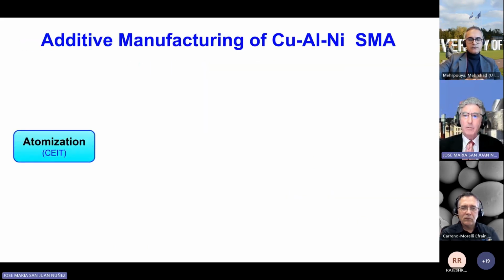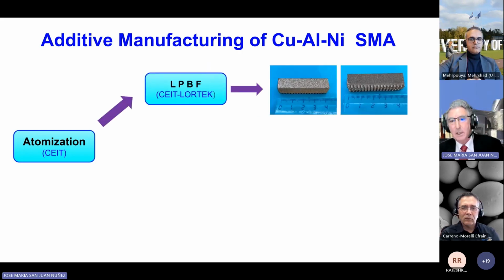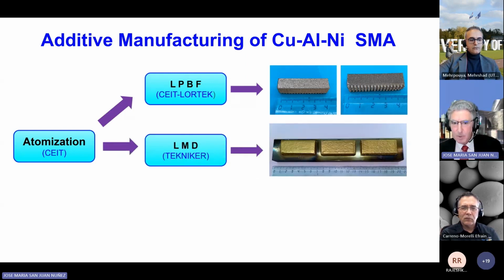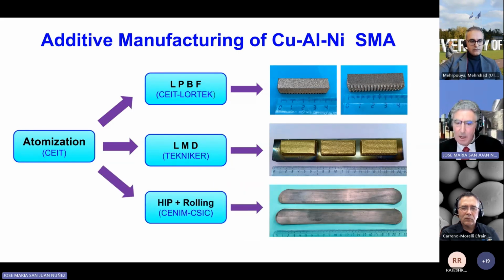Then, for the production by additive manufacturing, we work in different aspects. As it is a powder metallurgy technique, the whole process begins with the atomization of the material. And then we explore 3 different lines. The first line is to produce the massive material by laser powder bed fusion, in collaboration with our partners in the project. But we have also been working on laser metal deposition with other partners, and also we produce the material by the classical metallurgy route by hot isostatic pressing and hot rolling in order to have a reference material, because this strongly textured rolled material is up to now perhaps the most performant material in this kind of polycrystalline alloys.